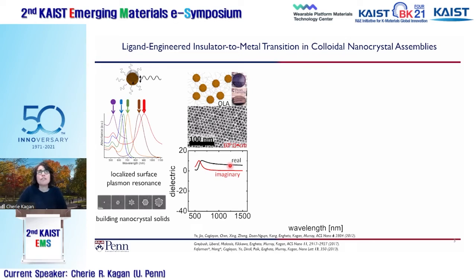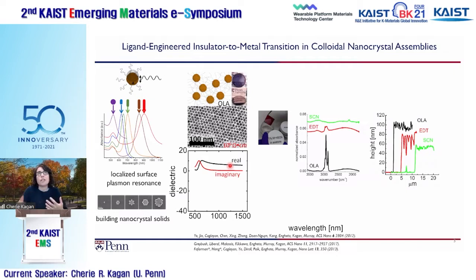If we want to use these materials for their functional properties in electronics or optics, often what we want is something more conductive, to allow electrons to be delocalized over these systems. The community has done a lot with what we refer to as ligand exchange, the idea that you can replace the ligands on the surface of the particles with something new. Today I'm going to focus on extremely simple examples, where you cast a film of these particles, as in this example, and dip it for a short time in a solution of the new ligand, and you can replace the parent ligand with the new ligand.